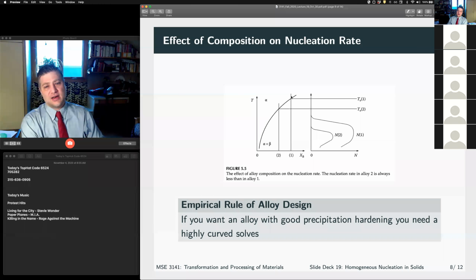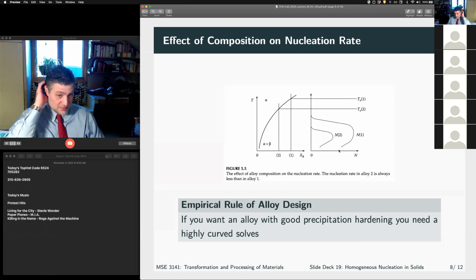That the greater my supersaturation for any given temperature, right? If I quench down from the single phase region into the two-phase region here, alloy 1 has a higher degree of supersaturation than alloy 2. It also has a larger degree of undercooling because of that. And therefore, we're going to have faster nucleation, right?